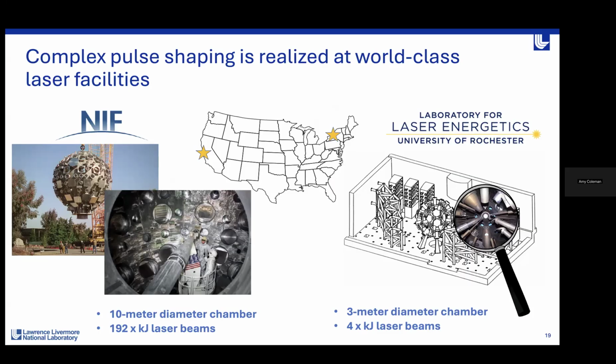And there's a lot of similarities between these two facilities. Typically, we have a chamber. As you can see here, we've got the NIF chamber and the Omega chamber, and this is where the experiment occurs. So we have our target package in the chamber, we have our diagnostics in the chamber, and we create our X-rays in the chamber at these facilities by irradiating a foil.